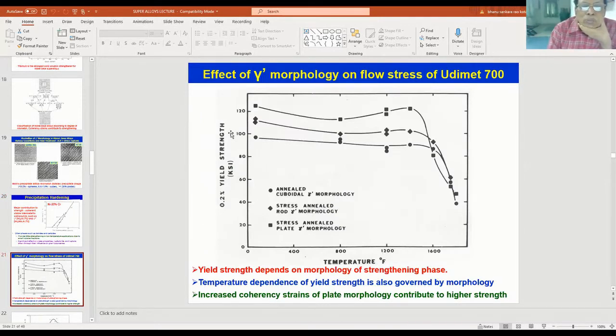You can see here yield strength has been plotted as a function of temperature with the different morphologies. You see, you have the cuboidal morphology. This is the strength that varies as a function of temperature. If you have a rod type of gamma prime, the strength goes up like this. If you have plate type of gamma prime, strength goes up like that.